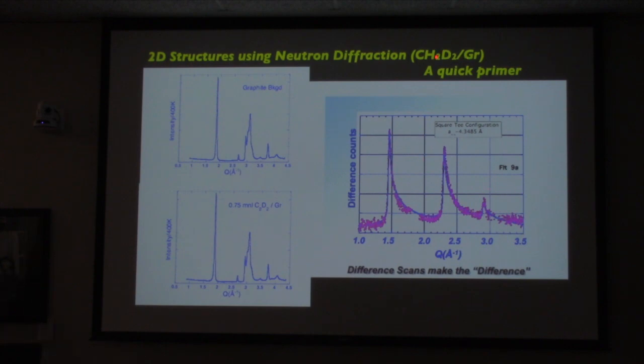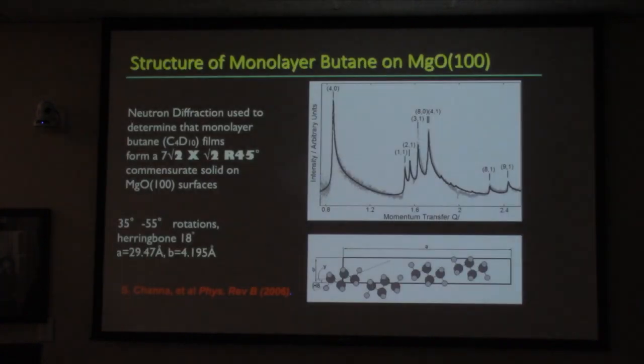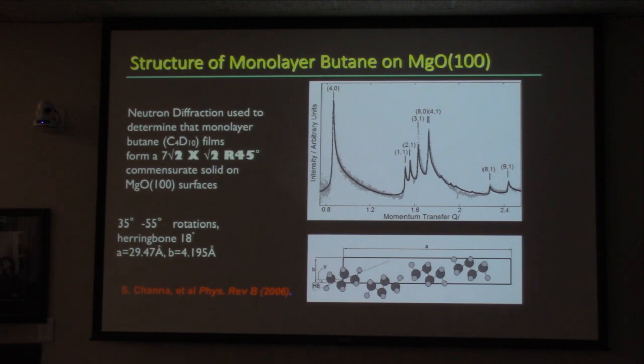The other interesting thing is that there's a strong quadrupole moment for acetylene, and so even though it sits on that six-fold graphite surface, it forms a square T. And that fit actually tells you that it's a square T and they're separated by about 4.5 angstroms, the lattice. That's not the only thing that we did, and now I'm going to run through them quickly because there are a bunch of examples. This turns out to be butane sitting on a magnesium oxide surface, and we know a lot about that. This is really crystallography in 2 dimensions, and it's pretty tough actually to do.